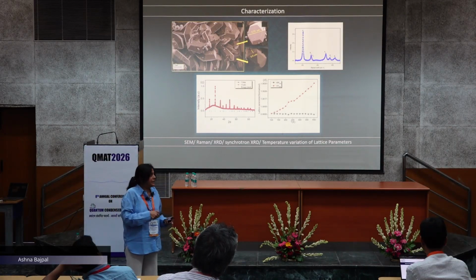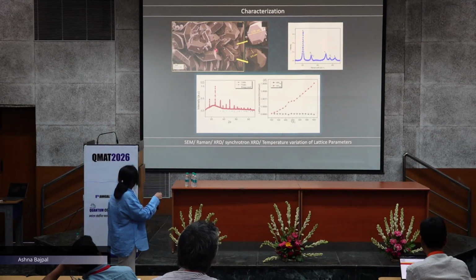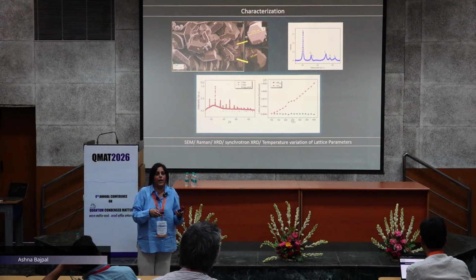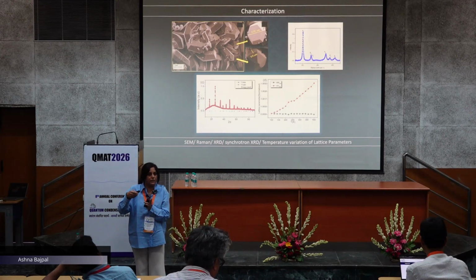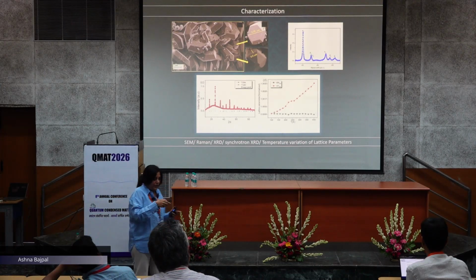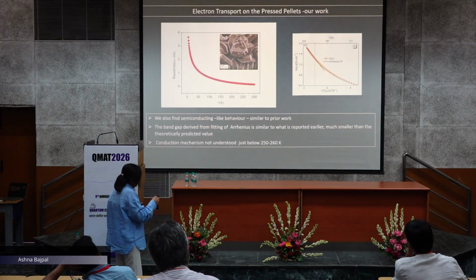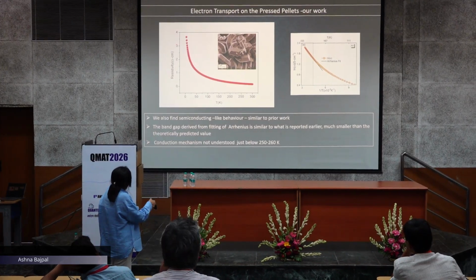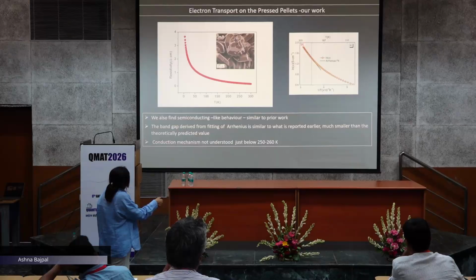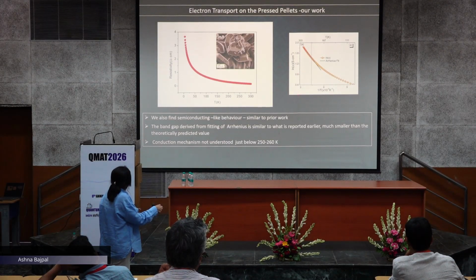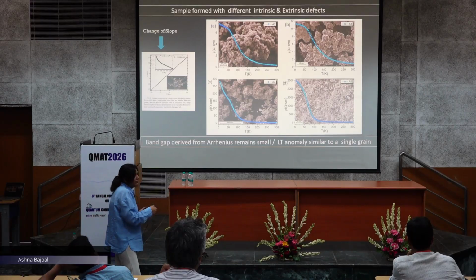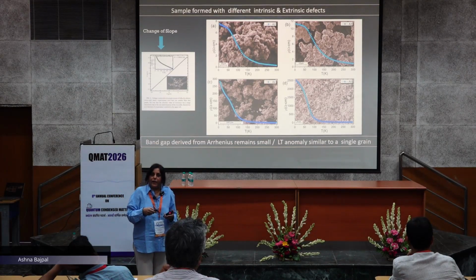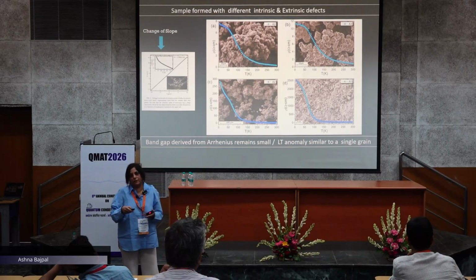So by variation in the synthesis parameters, we synthesized this compound, and we also found that the band gap derived from Arrhenius fitting, first of all, the Arrhenius fitting is in a very limited temperature range near room temperature, just a 30 to 40 Kelvin range, and the band gap is again 30 to 40 milli-electron volts. So, as I said, we found this semiconducting-like behavior, and Arrhenius fits only a very small temperature window, 200 to 300 K, and so we made Ru rich and Ru deficient samples, and we also played with the morphology, the grain size and grain boundary density.